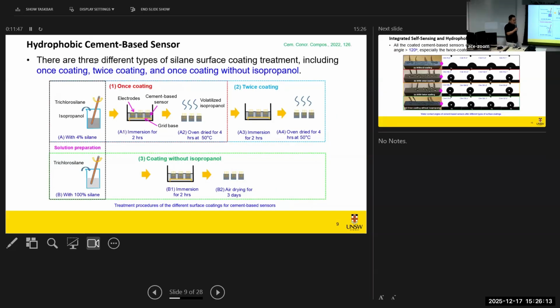So here, to improve the serviceability and the durability of cement-based sensors, we try to develop hydrophobic cement-based sensors using silane surface coating with isopropanol. You can see the preparation procedures shown here. Basically, we have three types of coating treatment: once coating and twice coating with isopropyl, and the third one is once coating without isopropyl.